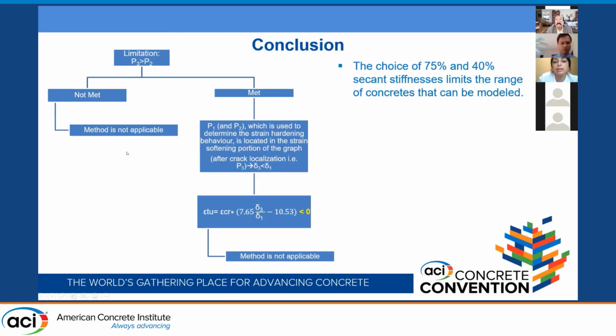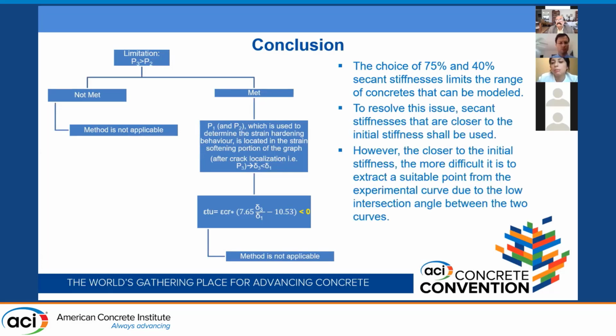So as a conclusion, we can say that the choice of the 75% and the 40% secant stiffnesses limits the range of the concretes that can be modeled. What does that mean? If 90%, for example, and 95% of the secant stiffnesses were used, this concrete could have been modeled. However, it's going to be more difficult. Why? Because it's going to be hard to extract a suitable point from the experimental curve because of the low intersection angle between the two curves, which are the secant stiffness and the experimental curve. The bottom line, it's a simplified method, but very limited.